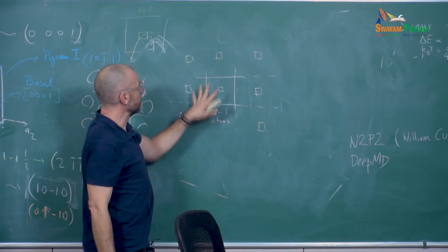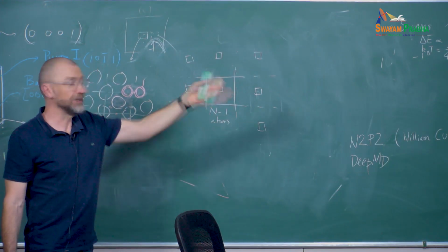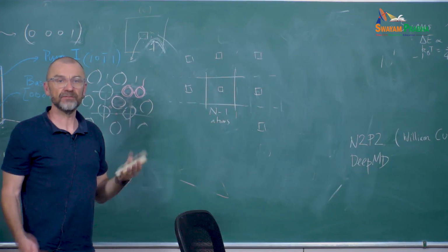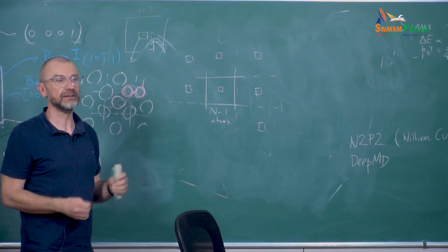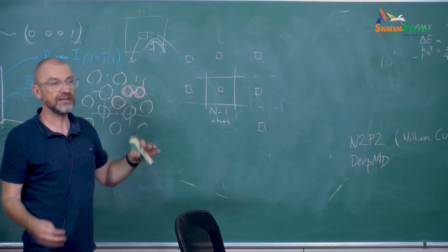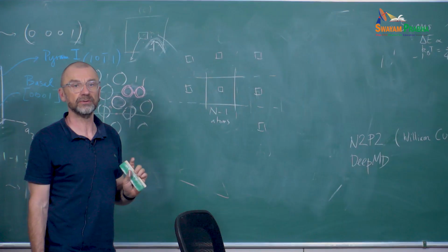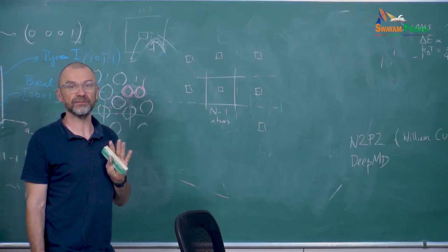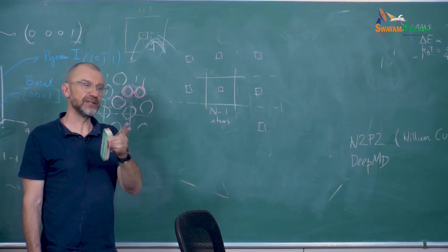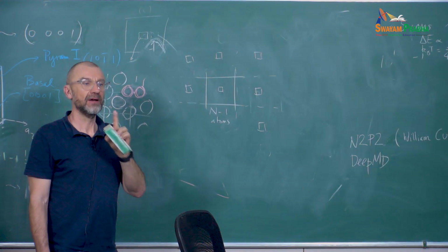But now imagine that I take that cell and I do an energy minimization, and I'm going to get an energy. From the energy that I compute, how do I get the energy of the vacancy? Because the energy that I'm going to get is the energy of the full cell here. It's the energy of these n minus 1 atoms. So how do I now extract the energy of the vacancy itself? Yeah, but what is important is the cohesive energy for how many atoms? Less than 1. Less than 1, right?